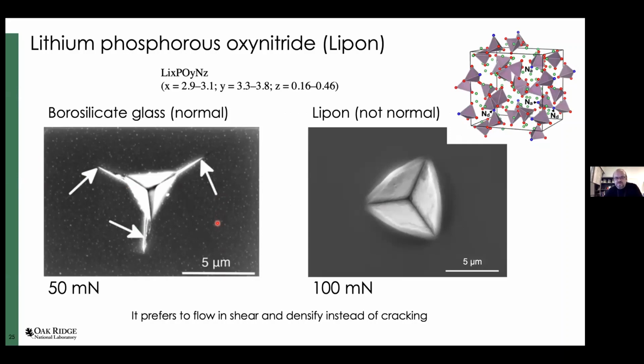So this is a simple comparison of a commercial borosilicate glass, which has glass formers inside, so it has a pretty rigid structure, and LiPON indented by the cube corner. This was indented to 50 millinewtons, and this is to twice the load. And you can see that LiPON deforms, shows very substantial pileups. It deforms in shear without any evidence of cracking. So this is very high load indentation. The nanoindenter went down to more than 2 micrometers into the material without producing any cracks. So this unusual behavior has something to do with the structure of LiPON. That's why it behaves so abnormally.